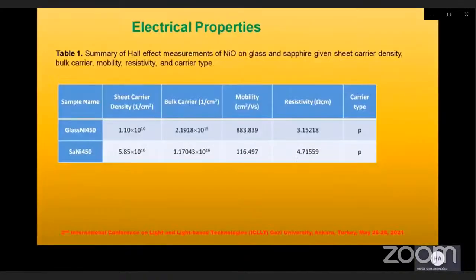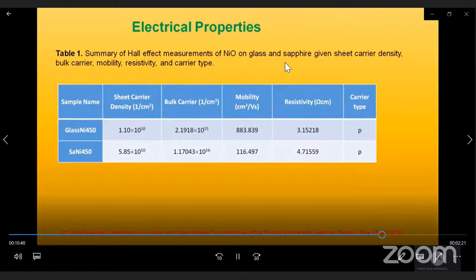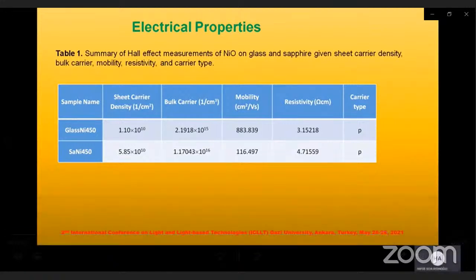Electrical properties. Hall effect measurements were made at room temperature to investigate the electrical properties of the films. Van der Pauw's geometry was used to measure Hall voltage and resistance. It was made for films with gold contacts produced with a mask prepared according to Van der Pauw geometry. The formation of the ohmic contacts was confirmed before the Hall measurements were taken. During the measurement, a magnetic field of 0.1 Tesla, 100 nanoamps current, and 5 volts voltage were applied, and the results were summarized in Table 1.